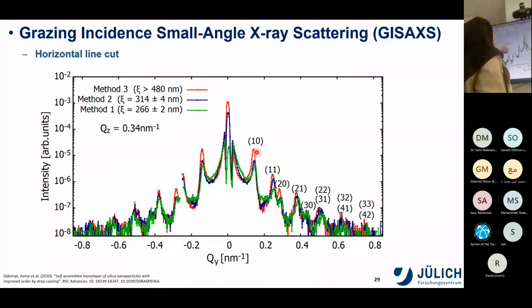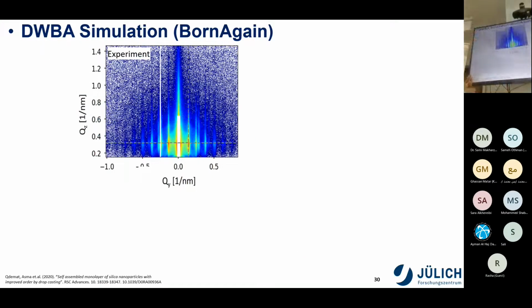For indexing, I indexed the peaks according to an assumed 2D hexagonal lattice with a spherical particle size of 50 nanometers. I then calculated the coherence length, taking the resolution of the GALAXI instrument into account and fitting the first-order peak with a Lorentzian profile. This gave me, for the monolayer in method 3, more than 480 nanometers, which is higher than the resolution of GALAXI. It's around 500 nanometers.